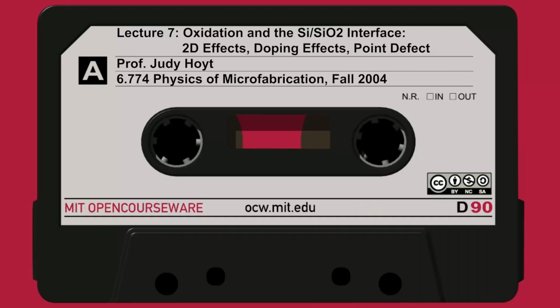Doping effects on oxidation. So besides the oxidation injecting interstitials, people also noticed that at low temperatures, depending on the wafer doping, they would get a different oxidation rate. So this is kind of interesting. I'm plotting oxide thickness versus time. A is lightly doped silicon, 10 to the 15th. F is 3 times 10 to the 20, much more heavily doped N-type, with phosphorus. At high temperature, not so much of a dispersion, but at low temperature, a large dispersion.